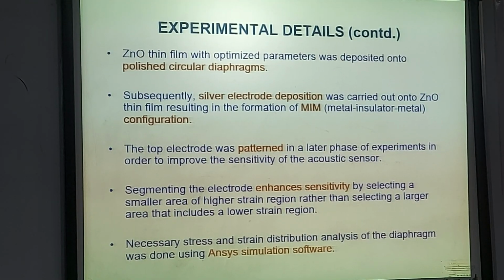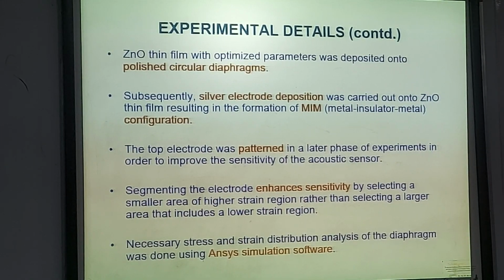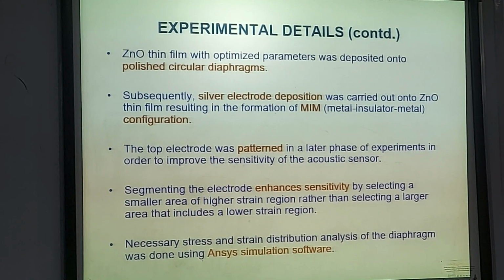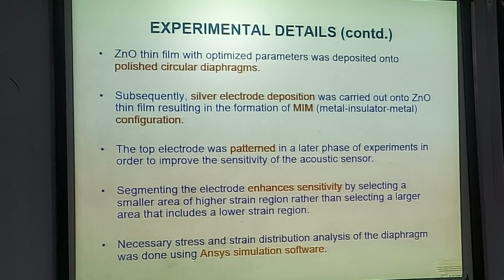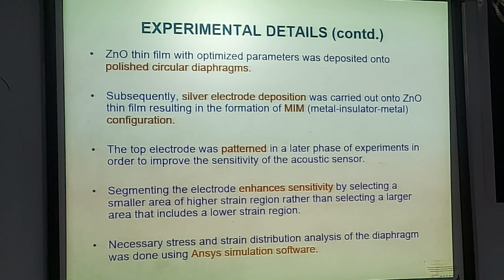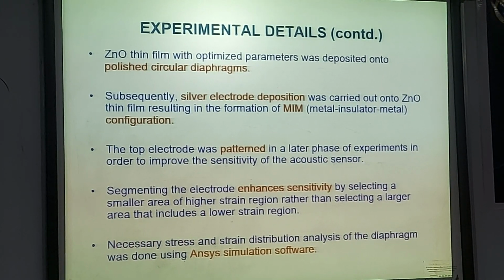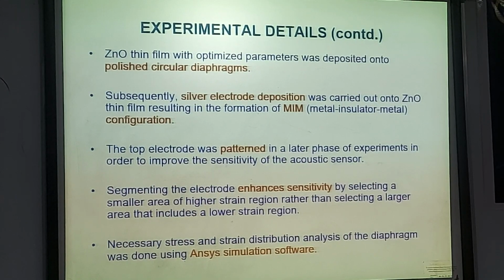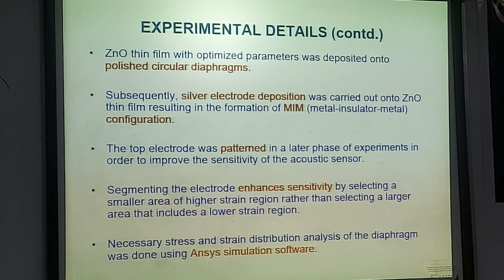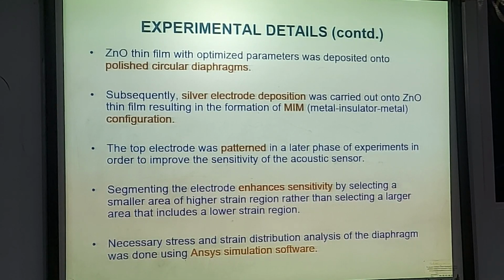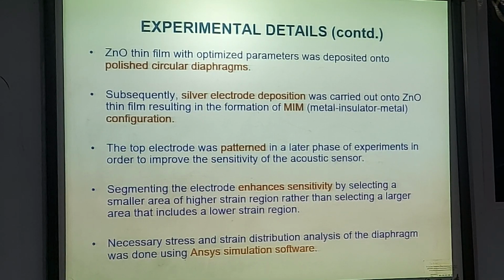Then this zinc oxide thin film with optimized parameters was deposited onto polished circular diaphragms. Subsequently, silver electrode deposition was carried out onto the zinc oxide thin film, resulting in the MIM structure, metal insulator metal configuration. The top electrode was patterned in a later phase of the experiment in order to improve the sensitivity of the acoustic sensor, and we found that segmenting the electrode enhances sensitivity. Necessary stress and strain distribution analysis on the diaphragm was done using ANSYS simulation studies.